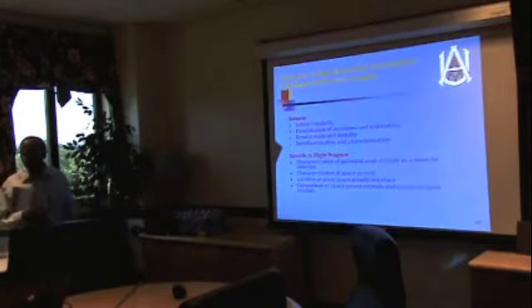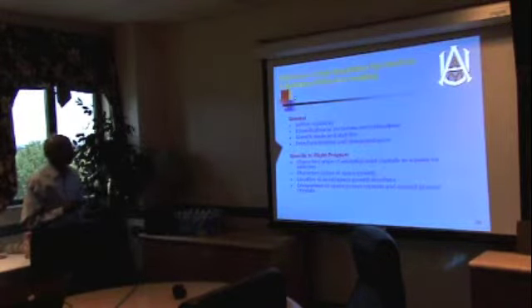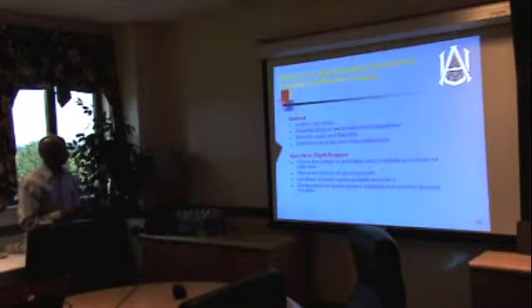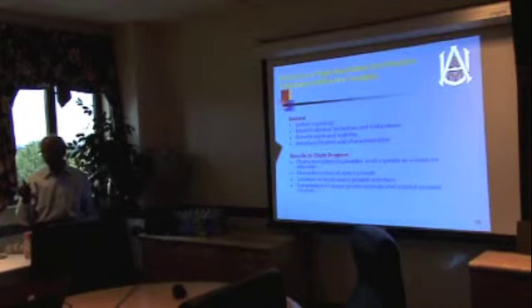We also did high resolution synchrotron X-ray diffraction measurements at the Brookhaven National Lab. The objective of this was, in general, to check the lattice regularity, that is, how the molecules and atoms are aligned in the crystal, and the identification of inclusions, because if there are defects in the crystal, either air inclusions or particle inclusions, then the diffraction pattern will show us the effect. Also growth mode and stability, interface location.